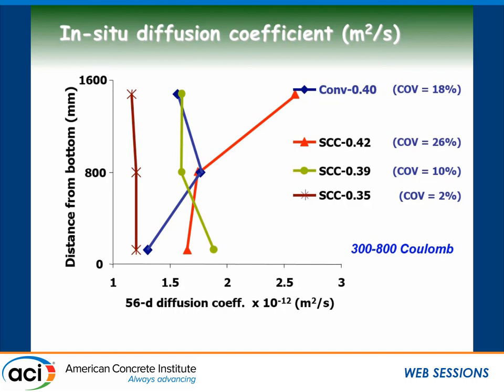Now what happens here if we use a 0.42? 0.42, again, you have values, and on the top you have much higher value because of the surface settlement and the effect of bleeding. Coefficient of variation of 26%. And you can bring that back if you were to add a viscosity modifying admixture, where the surface settlement goes back down, you build viscosity, and you get more or less homogeneous behavior.